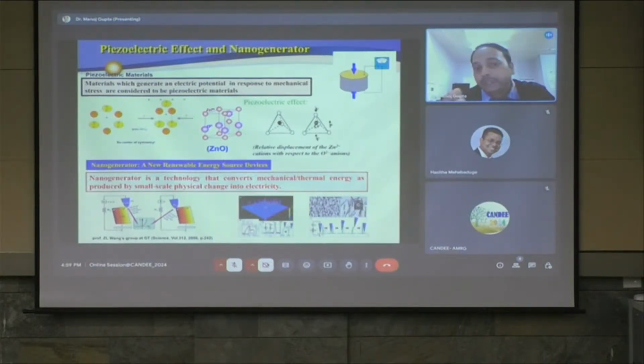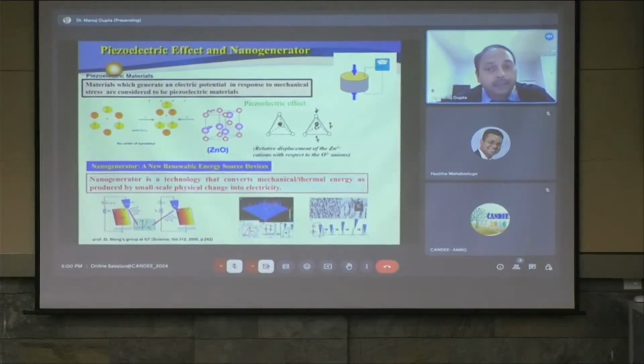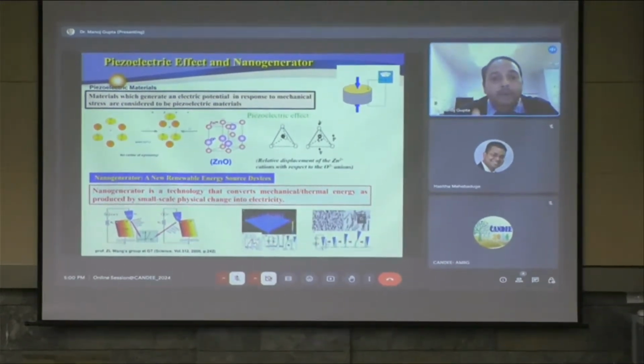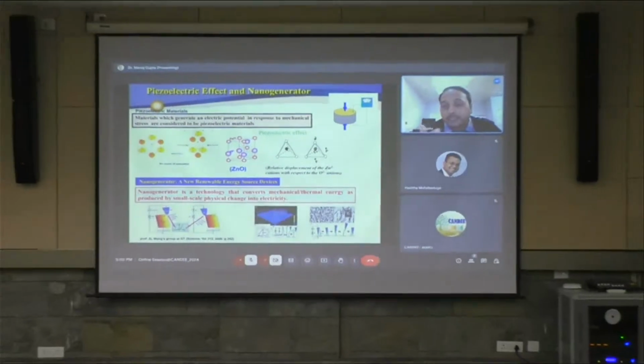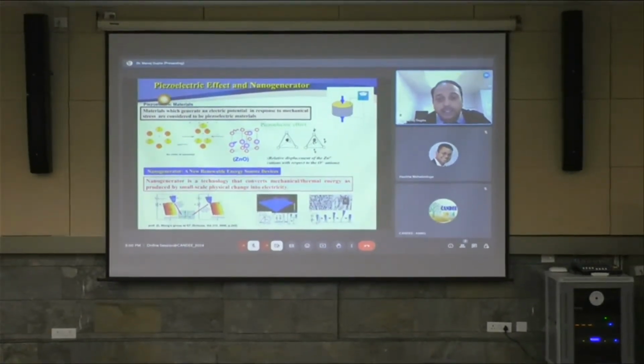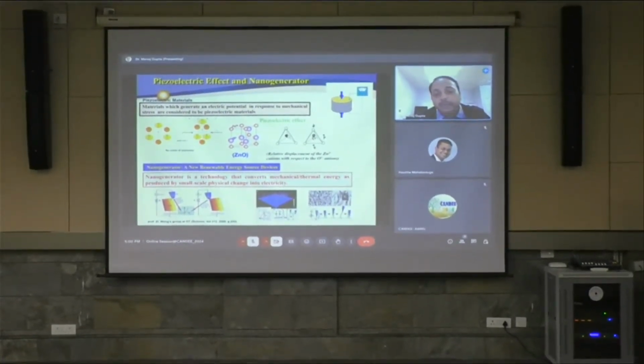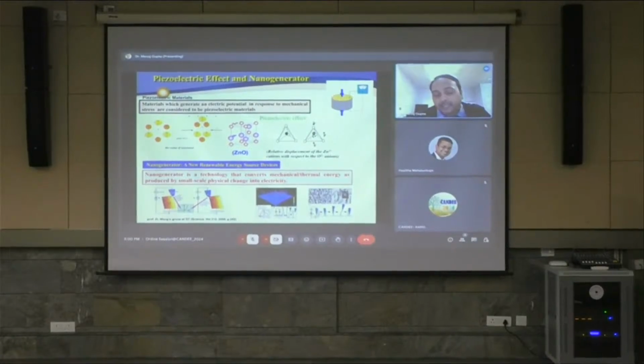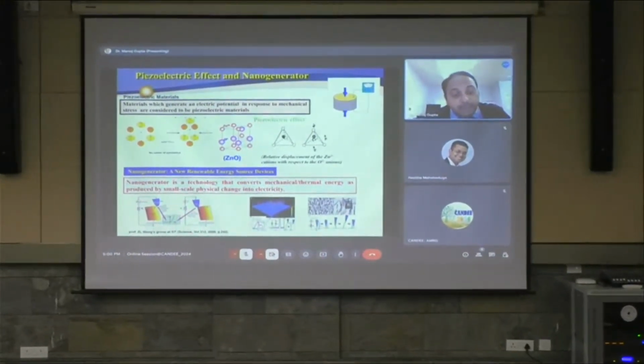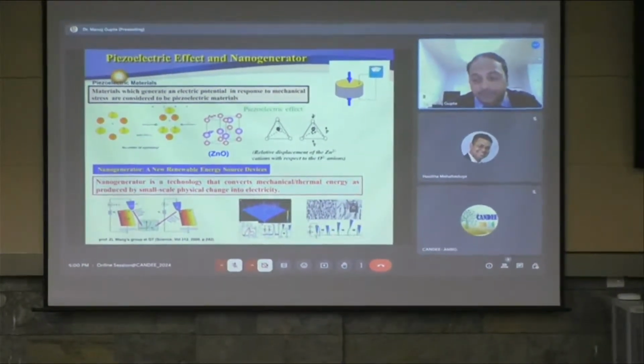So here we consider zinc oxide. If you apply some stress, compressive stress or strain, there is a relative displacement of the zinc cation with respect to the oxygen anion, which creates electric dipoles, permanent electric dipoles in the C direction. And this is the origin of piezoelectricity. Many other materials are also there, like lead zirconium titanate, barium titanate, right?